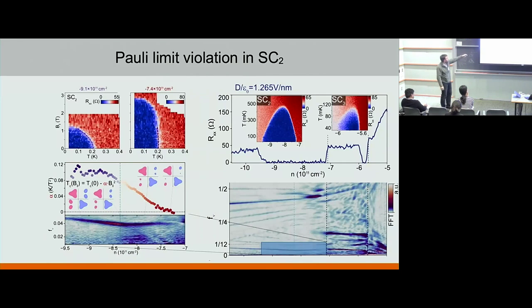In this quadratic term, the prefactor is essentially constant, more or less, while you're in this phase. We actually did cross-check experiments where you go sufficiently low in displacement field, where the whole phase becomes just this superconducting phase, and you only have a constant phase here. But on this other end, where you have this weird elongation, you just use a small portion to fit this alpha. You see that this alpha is linearly dropping off as this pocket gets smaller and smaller.